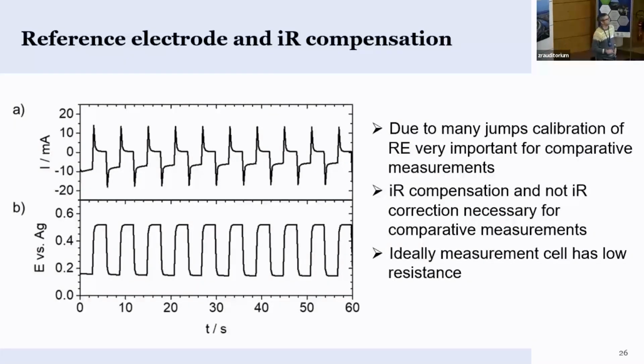Then you really need, when you do degradation by jumping up and down in the potential, and the absolute values, if you want to compare different systems, it is quite important to really hit the exact potential each time. But the reference electrodes we use are not necessarily the best. A small reference electrode is needed to make sure that they are stable and that you actually hit the potential that you're supposed to hit. There's also something like an IR drop if you have a large current. So in fuel cells, it's important to have a large current density, but if you have a large current and some resistance in your cell, that also means that the applied potential, what the potentiostat applies, and the one that is actually at the electrode are not the same. So it's important to know this resistance of your cell.